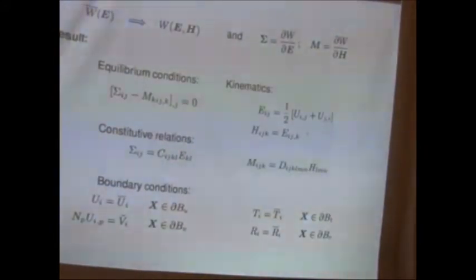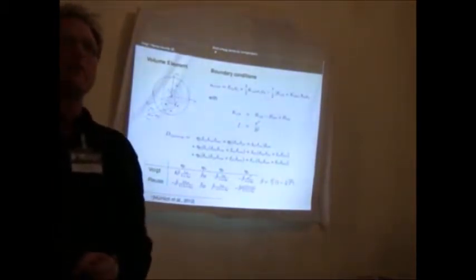You mentioned that you have 4 independent material constants. So you have 4 independent material constants in your formulation? Only for the gradient part. Good question. Let's say we start with 3 material parameters in the classical setting. We have the porosity, and we have Young's modulus, or two elastic constants for the matrix material. Now, if we go from the classical approach to the strain gradient approach, we have 4 additional parameters more.